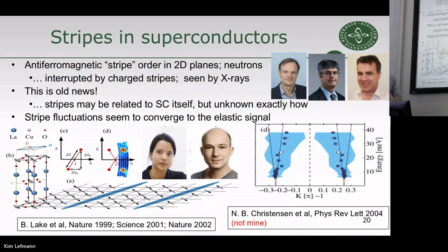So you will have magnetic diffraction peaks happening at a Q of 1/8 plus the antiferromagnetic ordering vector. So you will have it displaced by 1/8 from the normal antiferromagnetic Bragg point. And this is what we see in this data very, very nicely.